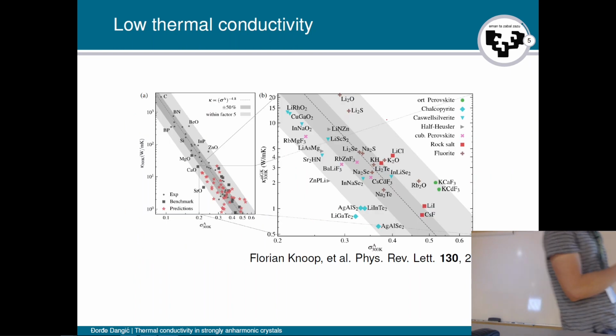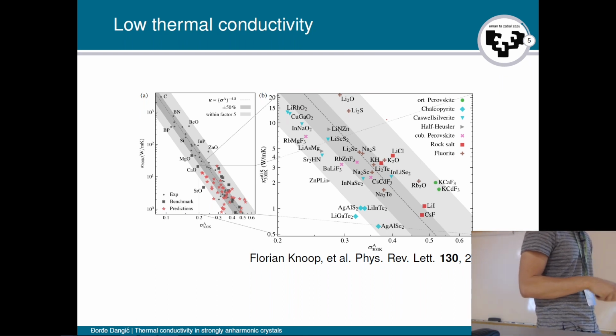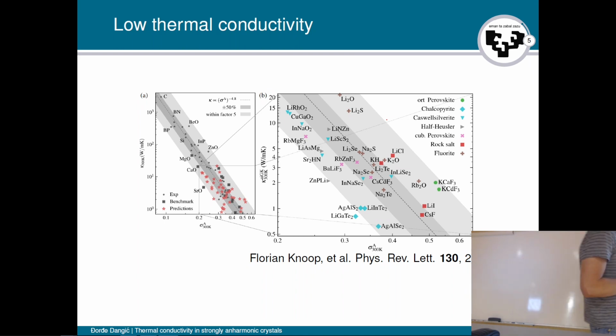So, to show the importance of the anharmonicity in the lattice thermal conductivity, we have this plot here from this publication. On the x-axis, we have the anharmonicity measure. So if this number increases, the anharmonicity increases. And then on the y-axis, we have the lattice thermal conductivity at room temperature. And as you can see, there is a pretty linear dependence between anharmonicity and the lattice thermal conductivity. So if we increase the anharmonicity, the lattice thermal conductivity goes down. And here we have some of the materials that exhibit very low lattice thermal conductivity. And we can see that they are mostly belonging to some common space groups.